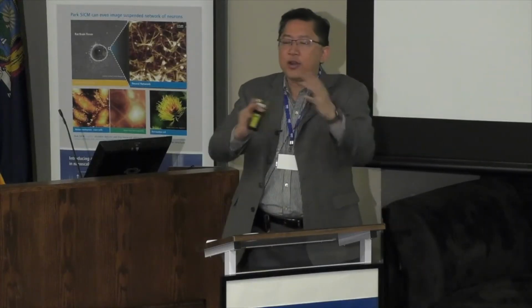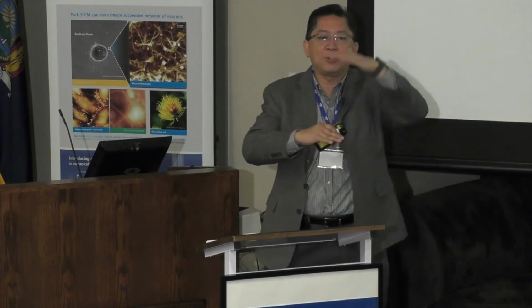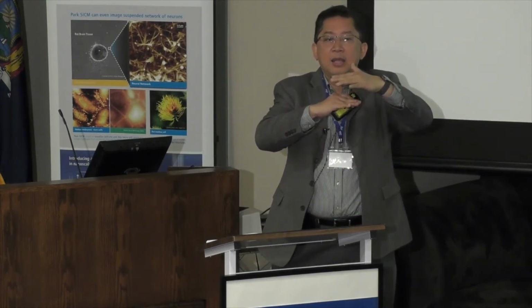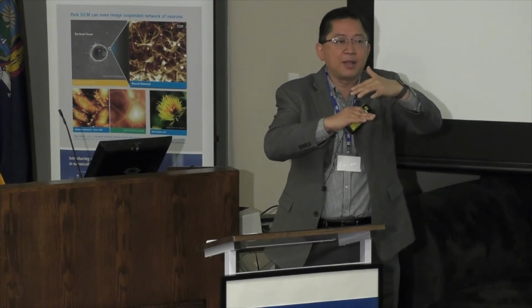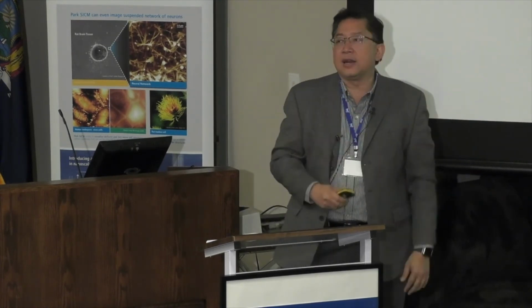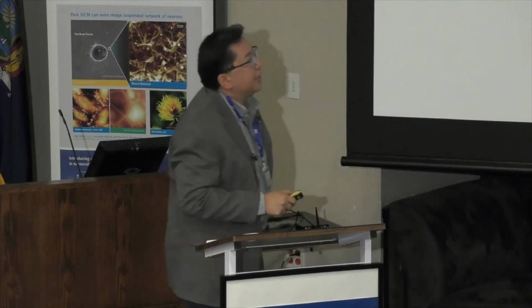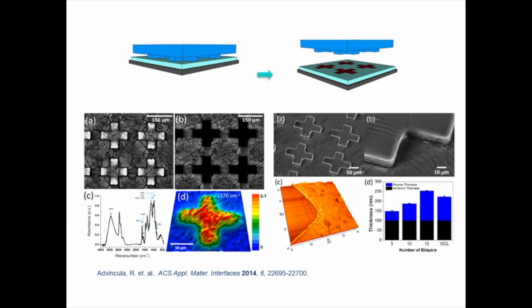So to make these origami folding particles, you need to have a soft and a hard layer. The soft layer is stimuli responsive. So the soft layer folds and makes the hard layer keep the shape. So we did this by using oxygen ion etching.